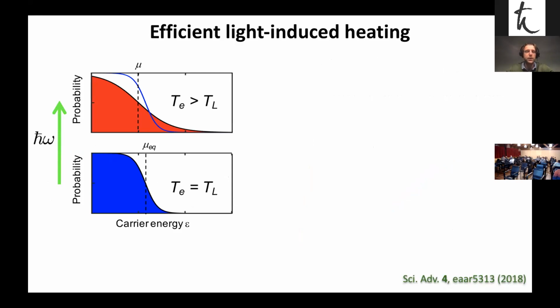So very briefly about these hot carriers. As I said, in the cold state, you have a certain Fermi-Dirac distribution broadened by, let's say, 300 Kelvin if you do this at room temperature. Then if you heat up the system by absorbing light, this can be light of any wavelength, from the UV, visible, infrared, microwave, terahertz, whatever you like. In the end, all that energy is absorbed in the graphene, and all the electrons share this energy, which happens on a very fast time scale, on the order of tens of femtoseconds. After that, you have this broadened situation with an increased electron temperature.